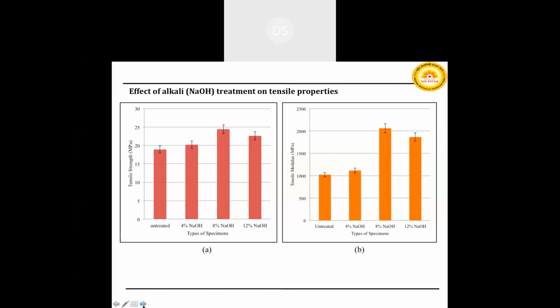In 8% NaOH treatment, some of the hydroxyl groups get removed, resulting in increased strength of the composite in comparison to the 4% NaOH treated and untreated fiber composite. But in case of the 12% NaOH treated composite, all hydroxyl groups and some part of the cellulose are also eroded, resulting in a reduction in tensile strength in comparison to the 8% NaOH treated reinforcement fiber composite.